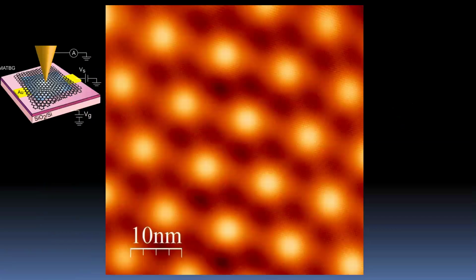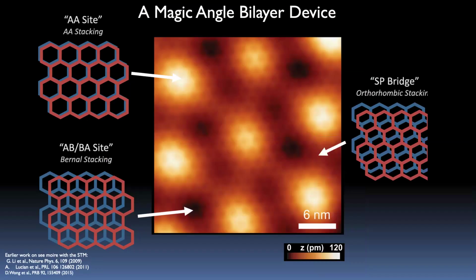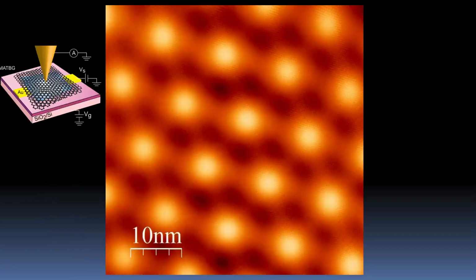Now, what you see in the STM images is a lot of information. For example, in this last image, on the very finest scale, which you can't really see on this projector, you see the carbon atoms. You see another Moiré structure, that's the BN underneath the sample, which has a Moiré structure with the bottom graphene layer, and then you have the Moiré on the larger scales between the two graphene layers. So you get all this information from the images.